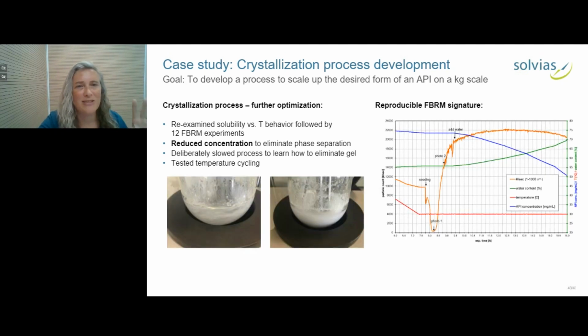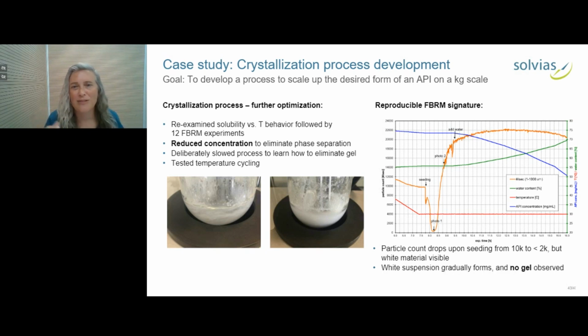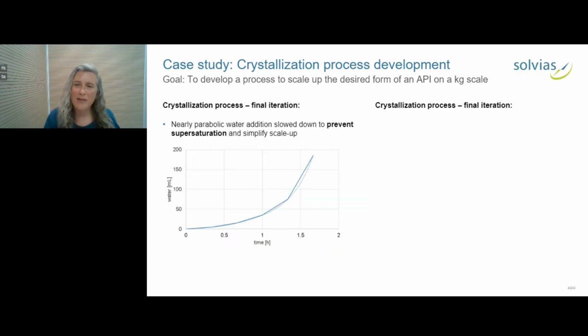We tested temperature cycling. Here we saw a very interesting FBRM signature where after you seed, the particle count drops, but we did actually see white material forming. So we had an unusual case where the FBRM probe was not able to pick up the particles so much, but we could show that there was a white suspension with no gel. And so then we worked on optimizing the process.